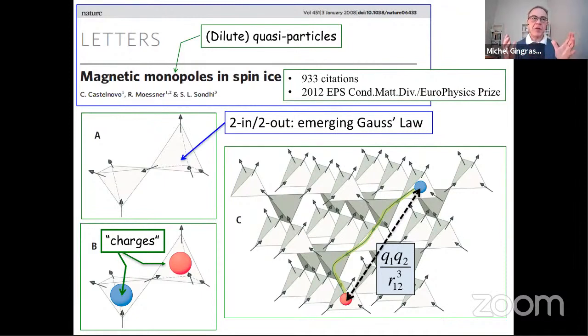So the spin ice state corresponds to a ground state where on each tetrahedron there's no divergence of this emerging field. But if you flip a spin, as illustrated in the bottom picture here, it's an excitation where you now have three spins pointing out and one spin pointing in, and you no longer have a divergence-free condition. So you have a source of this field, and the neighboring tetrahedron now has three spins pointing in and one spin pointing out. So this is a sink of that electric field or of its flux. And so the field theory description of the spin ice ground state looks like a Gauss's law. And these topological defects in the ground state of spin ice can diffuse around, they can move around.